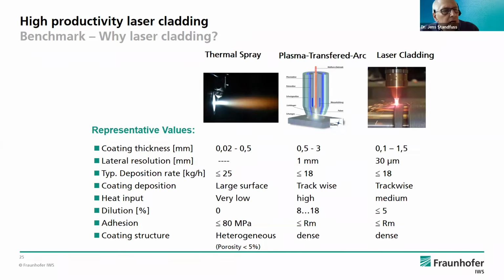If you compare this to laser cladding, you have a very high resolution. This can be good, but you can also use, as shown in the next slide, a very high efficiency through very wide tracks. The advantage is that the heat input is low, and especially the dilution of the base material, which leads to a change of the composition of the cladding layer, can be prevented. And so you have a very high quality clad.